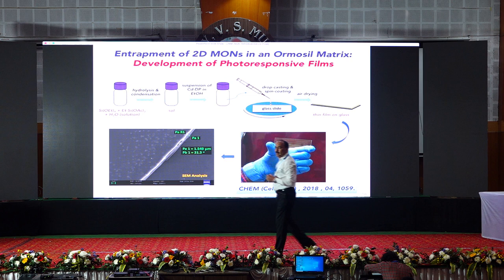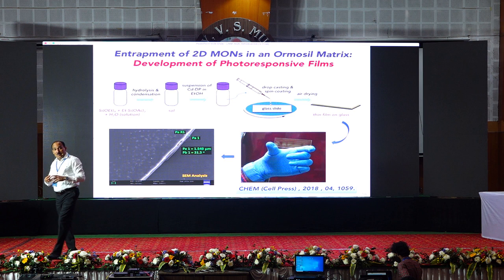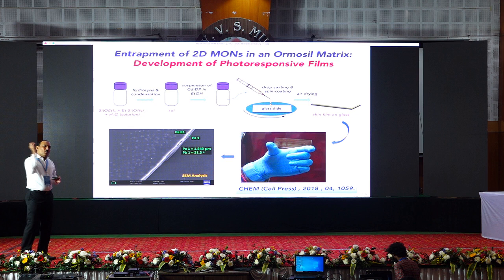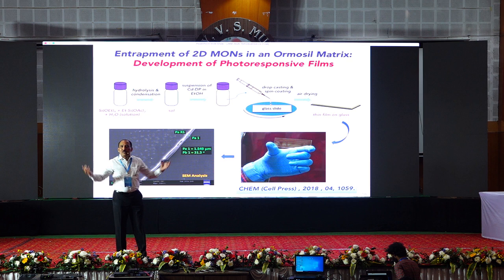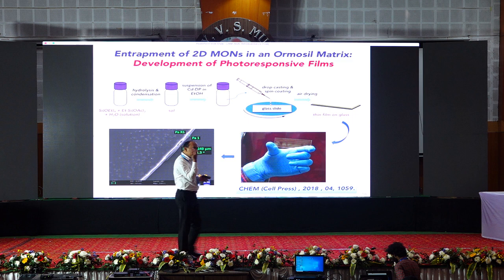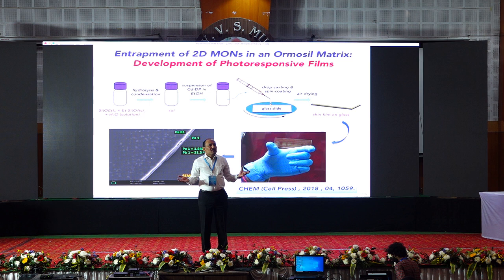Now, can I take it to the proof of concept? You have a molecular material with which you built a 2D material, and the 2D material is photoresponsive, but I want to use it for ophthalmic lenses, right? Normally, an organic compound you put into a polymer will leach out. But because now you have a 2D polymeric material, which gets impregnated into the polymeric matrix of the glass that you make, polymethyl methacrylate, and it's interwoven, there's no leaching issue. That is the beauty of 2D polymeric materials.